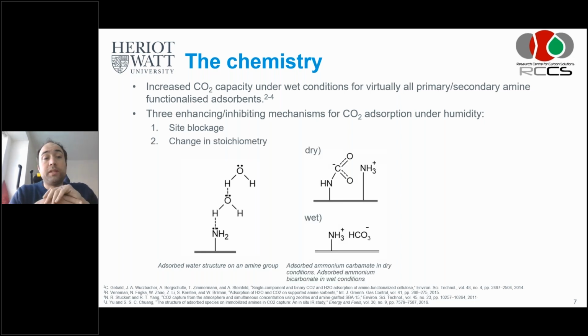Then secondly, the theory stated that there will be a change in stoichiometry. What you see in absolutely dry conditions is that you would form this ion pair, which is basically a carbamate and an ammonium group. So you have a negatively charged carbamate and here you have a positively charged ammonium group. But under wet conditions, that ammonium group can also combine with a bicarbonate group, which is the HCO3 minus here. That means that instead of two amino groups, because for carbamate you need an amino group, and for ammonium to form you need an amino group, you can bind CO2 with one amino group.